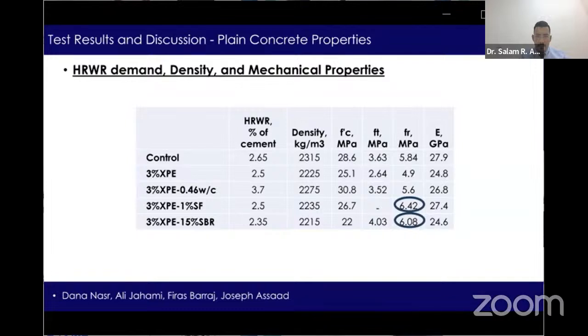Alternatively, when steel fiber and SBR were incorporated, we can note that only the tensile-related properties were recovered. For example, fr reached 6.42 megapascal when 1% steel fiber was added, and fr reached 6.08 megapascal when 15% SBR was used. For fibers, this can be due to a bridging effect that delays the formation and the propagation of cracks during tensile loading, which leads to improved flexural properties. For SBR, these polymeric latices are efficient to improve the adhesive bonding within the aggregate skeleton.